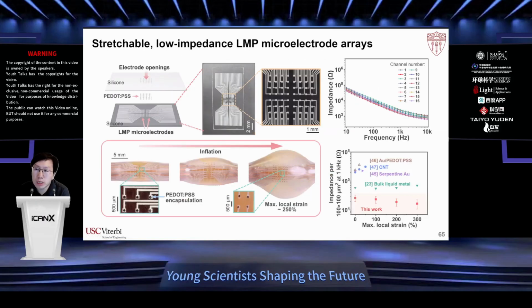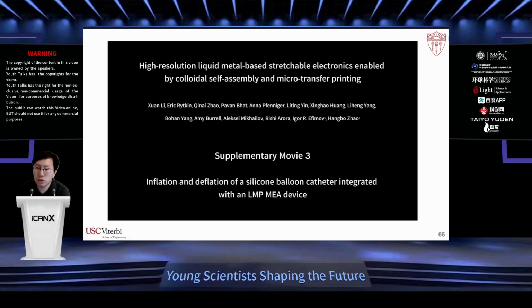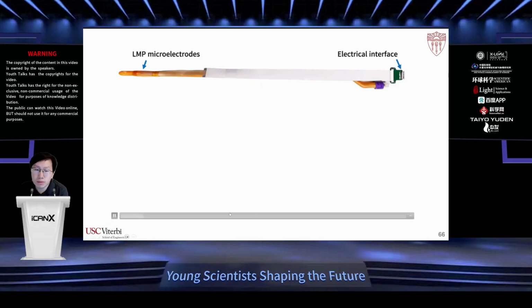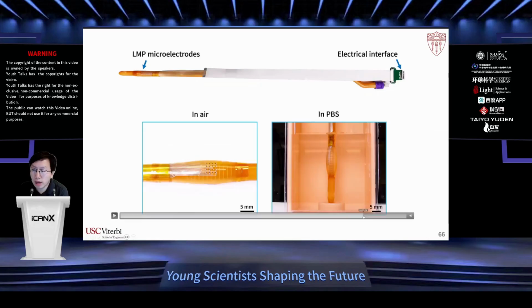And we can also make high-density microelectrode arrays and integrate them onto a balloon. As you can see here, it can undergo extreme deformation. And interestingly, the impedance of the electrode actually decreased as we stretch. It's very different from other conventional conductive materials. We think this is because of the increased conductivity as we deform the material. So this is the video which I guess I have to skip. This just shows the inflation of this catheter.